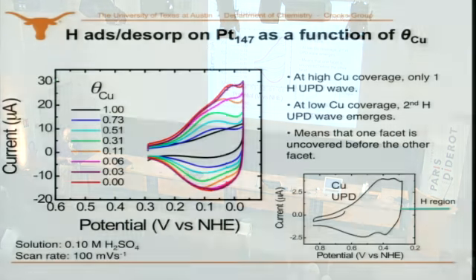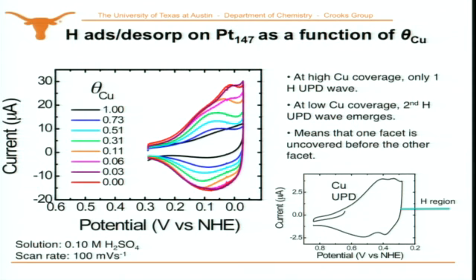So this is a slide. Here's the copper underpotential deposition again onto the 147 atom platinum particles. What we're going to do is deposit a little bit of copper, stop here, change the solution, just leave that little bit of copper on the platinum, and now do hydrogen deposition and stripping. And that's what this is. Now we're going to do another one. We'll stop here. It's all done on the same electrode with the same nanoparticles, the whole experiment.